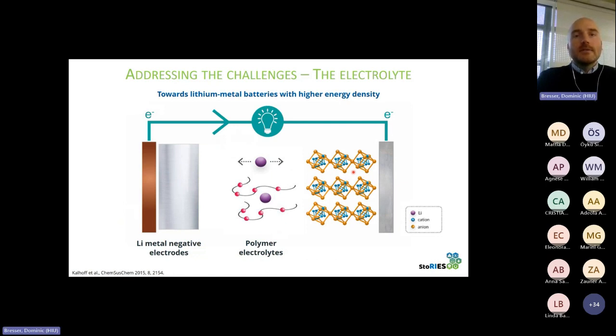So having said this, talking about polymer electrolytes in combination with lithium metal electrodes and NMC type cathodes, for instance. Having a more global perspective on the system, you see that we have a big excess of lithium. Because in a lithium-ion battery, where instead of lithium metal there would be graphite, the only lithium source would be the positive electrode. And here we have the positive electrode as lithium source, and we have plenty of lithium at the negative electrode.